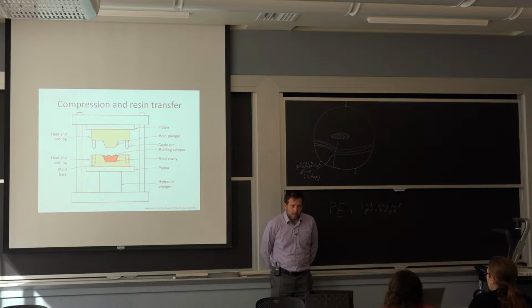It is tested, so if you buy a resin, you can subject it to a temperature ramp, a few degrees per second, and you say, I want it not to start losing weight until 200 degrees C or whatever your criteria is. And that's how you know if the resin from vendor A is better than the resin from vendor B.